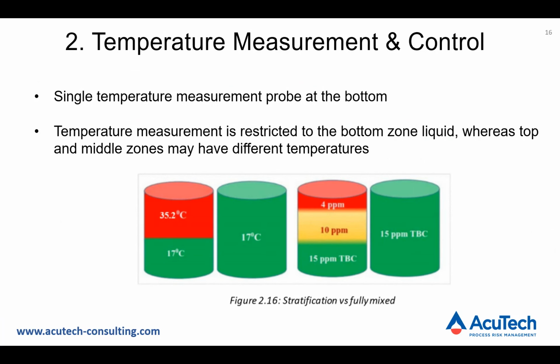Apart from the tank design and the issues with respect to the maintenance of the tank, there were some issues with respect to the temperature measurement and control system. The temperature measurement was restricted only to the bottom zone of the liquid, whereas the top and middle zones may have different temperatures because of poor mixing. As we saw, the modification was done without ensuring that the mixing would be adequate.